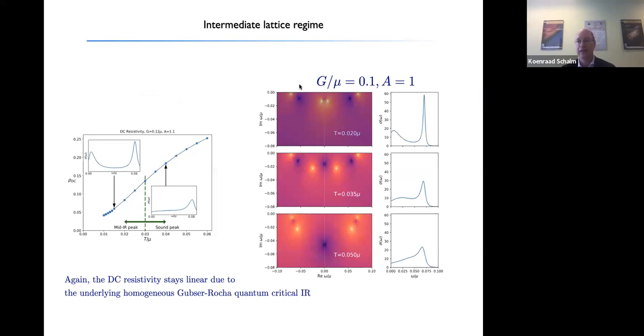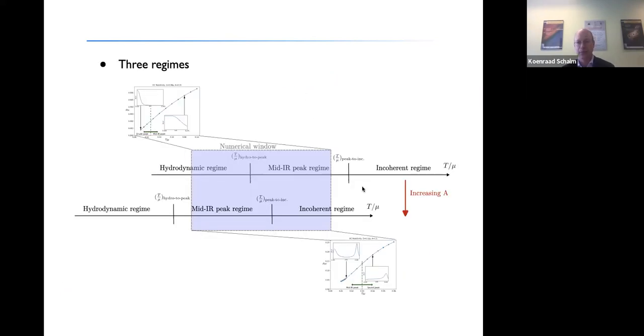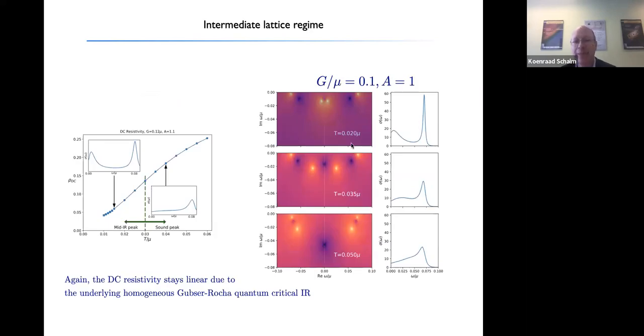But you can also try to study the system at slightly larger lattice potentials, the potential strength, to see what happens further. And even though Umklapp hydrodynamics itself as an analysis starts to lose its validity, you can nevertheless beautifully in holography study the pole structure of this system. And here you see the poles in the regime where we started earlier. These are the 2 peaks that have collided and moved off. And now I've zoomed out. And you also see the 2 Umklapp sound peaks. These are precisely these 4 peaks that I gave you in the analysis of Umklapp hydrodynamics.